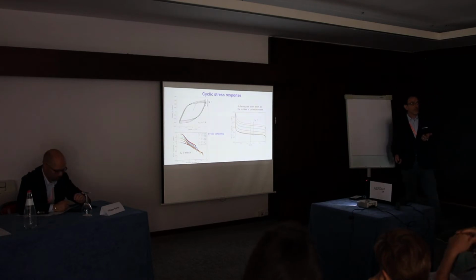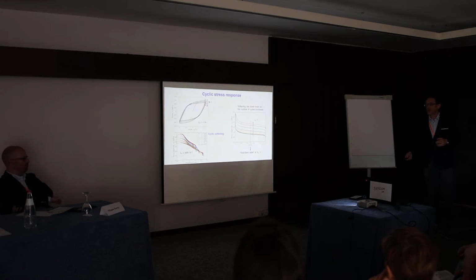Then we consider this plot and replot this trend using a linear scale, and we also normalize the number of cycles to the number of cycles to failure in order to detect the change of the softening rate. Here you can see that there is a sort of plateau. It is not exactly horizontal, but we can consider that the behavior at mid-life is representative of a stabilized state. So we consider this behavior for the modeling and fitting of the models.